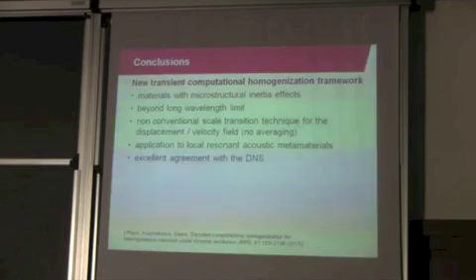So just to summarize, I presented the new transient computational homogenization framework for materials with microstructural effects, where by microstructural effects, in this case, I mean these local resonance effects, which go beyond the classical long wave length limit. It uses the non-conventional scale transition relations for the displacement and velocity, so not a simple averaging. And that's, in fact, the crucial point here. That's actually what does the whole trick.